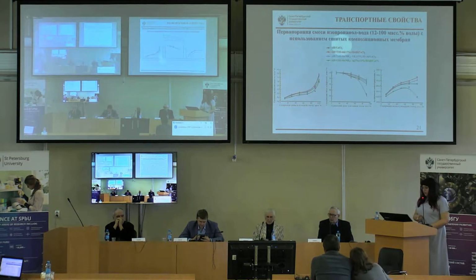To increase productivity of diffusion membranes, the selective layer thickness was reduced by creating composite membranes in which a thin selective layer was deposited on a porous polyacrylonitrile substrate. Composite, modified, and unmodified cross-linked membranes were also tested by evaporating a water mixture over a wide range of concentrations.